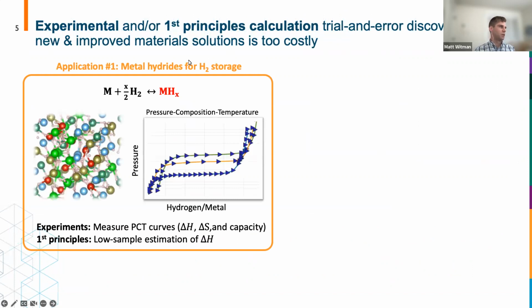So just to touch on a little bit more of the material science. We're going to be looking at metal hydrides for hydrogen storage, which is, you have a metal or high entropy alloy that can absorb hydrogen in this reaction. And how we measure that experimentally in the lab is we do these PCT curves. So we apply pressure, measure the hydrogen uptake, and here you see this phase transition that occurs in the material that allows you to store a large amount of hydrogen over a low pressure swing. So once you've gone in the lab and measured these PCT curves, you can get the delta H, delta S, and capacity for these reactions.